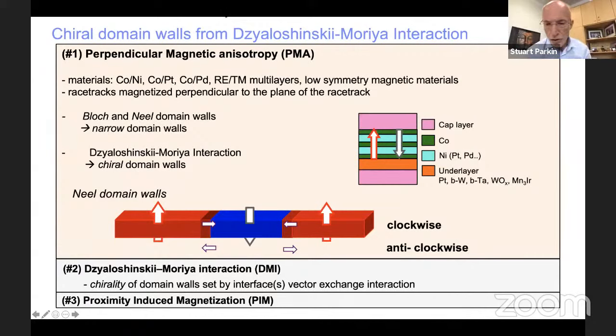What does that mean? As you move along the racetrack, the red moment rotates down into the blue moment, and you'll notice that it rotates in a plane perpendicular to the domain wall. This is a Néel domain wall. And when it rotates from a blue to a red direction, then you can see in the middle of the domain wall, the magnetic moment will be in the opposite direction, again aligned along the racetrack. So there's a chirality associated with these domain walls. And this, in some sense, is the first use of a chiral spintronic phenomenon. And as I said, these domain walls can be clockwise or anti-clockwise, depending upon the nature of this Dzyaloshinskii-Moriya interaction, which is really an interface interaction.